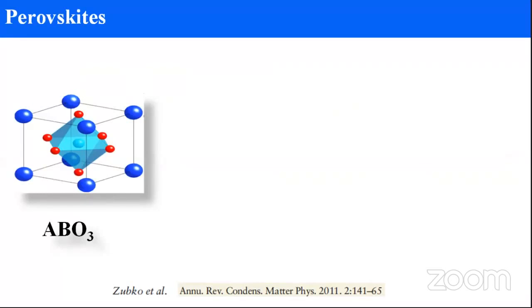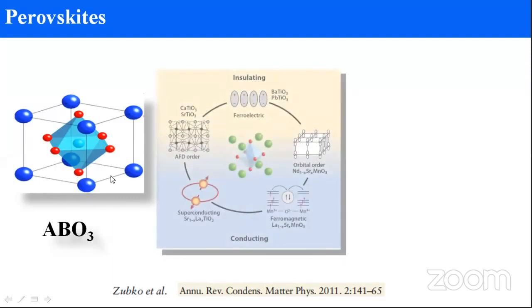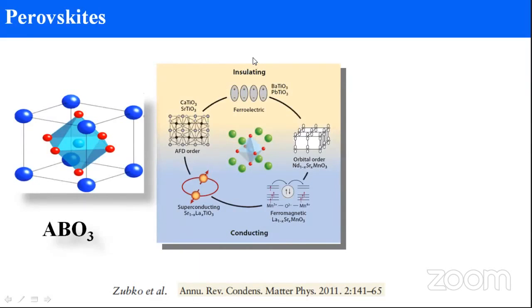Throughout my presentation, I'm going to present on a special class of material called perovskite materials, which has a very simple structure like ABX3. There is an A site, there is a B site with octahedra here. Why is this class of material important? Because we have quite an enormous range of properties on this simple crystal structure. If you want insulating materials with ferroelectric properties, you have lead titanate, barium titanate. You can also have conducting materials like lanthanum strontium manganate with ferromagnetic property. You can even have a superconducting material in simple strontium titanate.